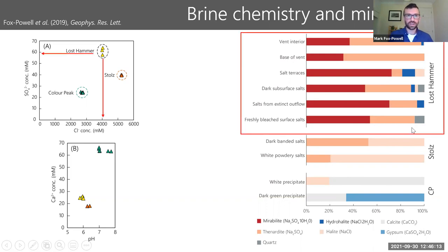Draw your attention to Lost Hammer here. The deposit here, these peach colored and red, these two major bars, the dominant minerals in this system are sulfate minerals, mirabilite and thenardite. Thenardite is simply the anhydrous form of mirabilite, and may well have dehydrated during transit and sampling. This is a sulfate-dominated salt deposit, but that's despite the fact that the brine itself is actually chloride-rich. By a couple of orders of magnitude, chloride dominates over sulfate. So this is a chloride-dominated brine forming a sulfate-dominated salt deposit.